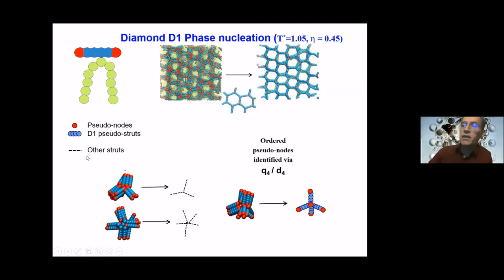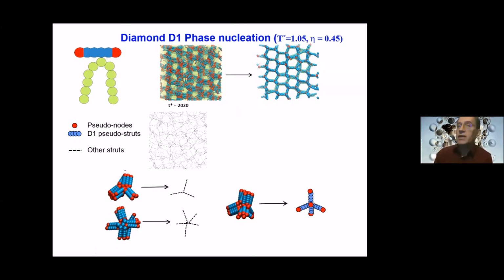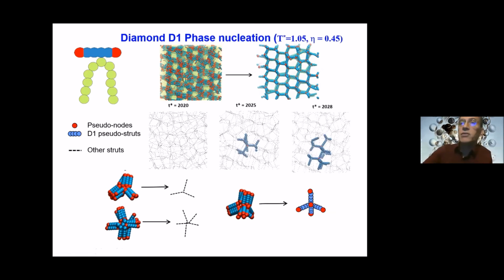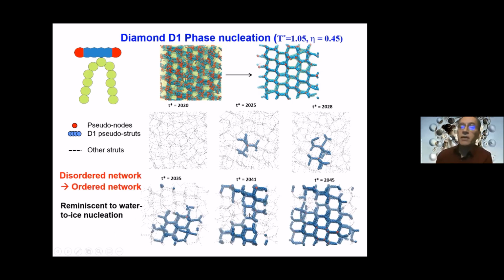But if they are not, so you have a different kind of symmetry, I will show the struts just by dashed lines. What you find is that from the beginning, very quickly, the system forms a network, but it's a disordered network. It's just all made of these struts, as you can see. And it's only after a long while that you start nucleating the ordered network. You start picking out this motif that will start growing and growing, and eventually will overtake the whole system as shown here. Interestingly, this disorder to order network transition resembles a lot what happens to water when it nucleates into ice through hydrogen bonding.